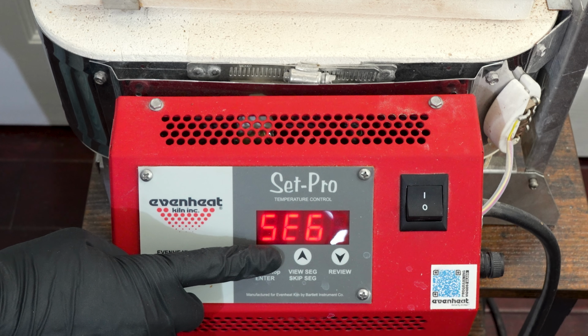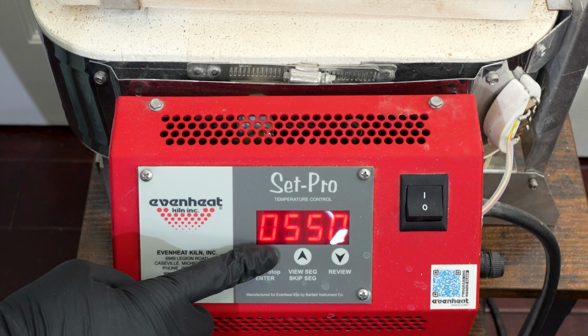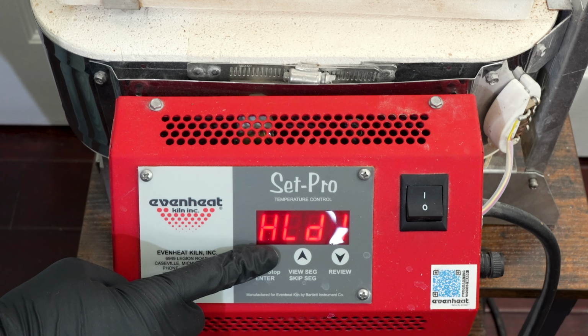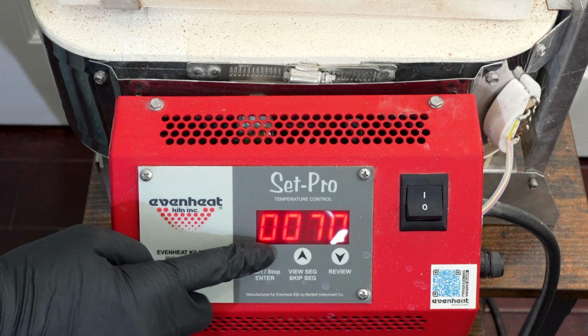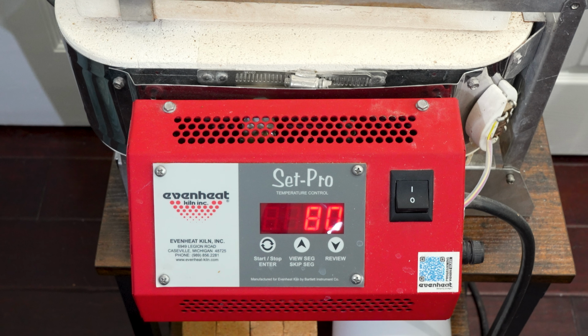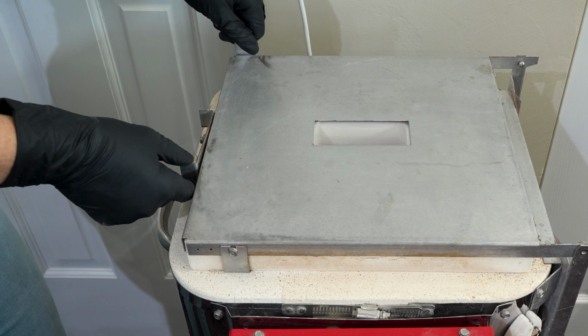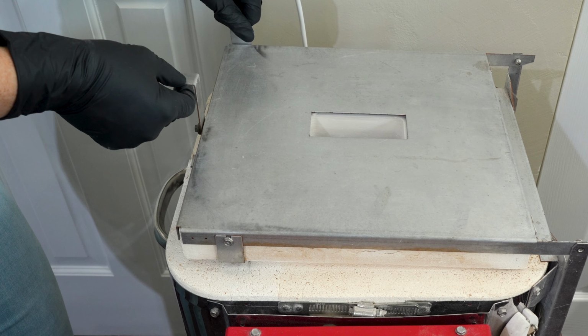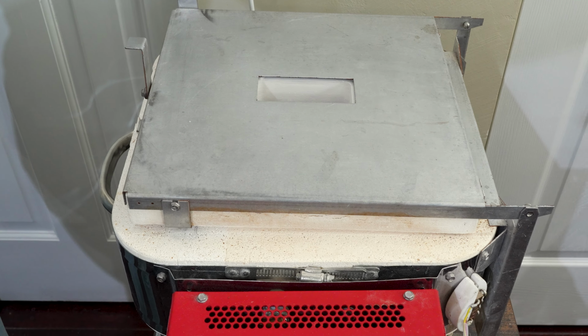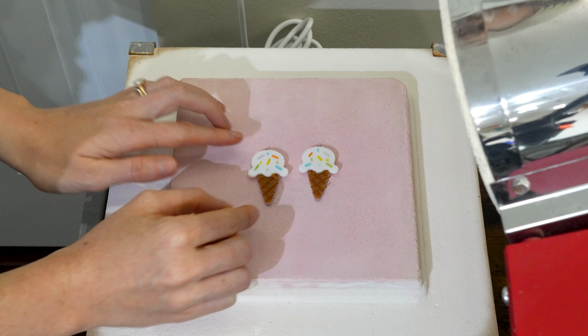This usually means ramping up quickly to around 550 degrees Fahrenheit, holding for about 20 minutes, and then cooling as fast as possible to room temperature. Vent the kiln slightly during this firing to avoid corrosion of the kiln's internal elements. Once the shelf has completely cooled, a project can be constructed on top of it.